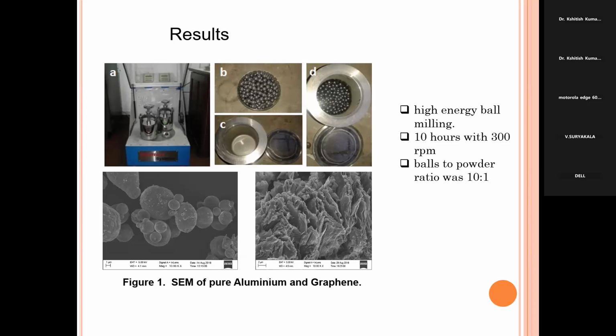But as this is a metal, we have taken a 10:1 ratio for the stainless steel balls. So in the jar we have put 10 grams of the aluminum and graphene powder, and put in the balls, and we have put it in the ball milling machine for 10 hours, and the rpm is 300 rpm, and the ball to powder ratio is 10:1. Okay, so the lower part is the SEM of the pure aluminum and the pure graphene.